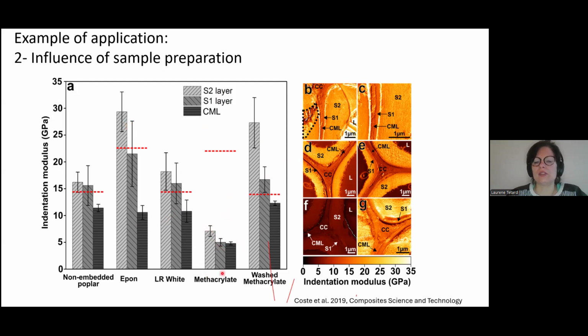And in some cases, for instance methacrylate, the microtome knife would smear the resin on top of the tissues. So when we probe, we are measuring the mechanical property of the methacrylate that's coating the sample, even though it's a very, very thin nanometer-thick layer. And it was really hard to retrieve the mechanical property even after washing the methacrylate. So for wood, it's not really a problem because we can section it without embedding it, like we see with the control. But it's more of a problem for instance for switchgrass or leaves or roots. If we wanted to embed those structures, we know that there's going to be an effect from the resin.